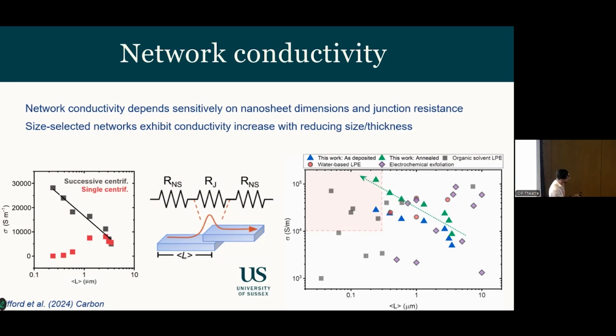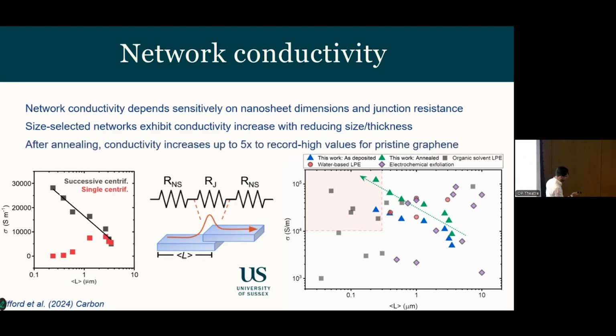So we're actually starting to see some behavior where the smaller sheets are more conductive, not only than the biggest sheets, but they're more conductive than many other reports for graphene and for nanosheet networks in this area. So you don't have to use very big, thick graphene and compress it and do very circuitous things like some of the people over here do. You can actually have some inherent behavior that's associated with the processing that we do that allows us to make networks which we believe have improved transport.